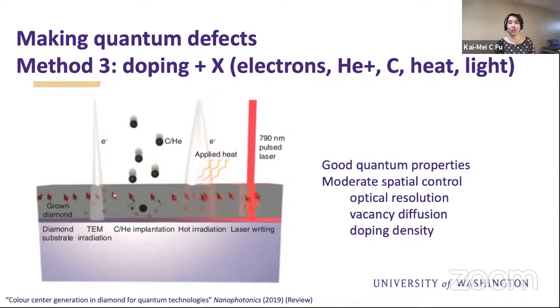But then you do something else that's less damaging to create the vacancies. And this might be electron irradiation. It could be carbon. Likely, it actually looks better if it's a very light ion irradiation. You can also use heat or optical irradiation to create vacancies where you want them. So you have the nitrogen everywhere, but then you get the NV centers where you want them. How good you can get with this is still under investigation right now. And this is a really nice review of all the different ways to make NV centers down here.